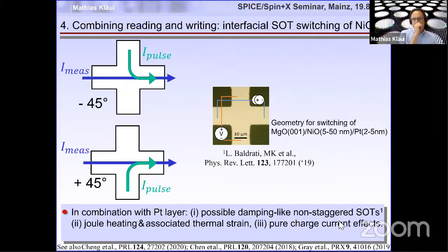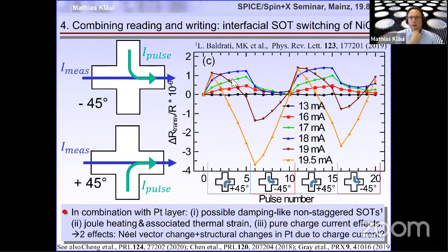And so this is what it looks like. It looks very messy. You have a lot of effects. For small current densities, as shown here, it's more or less flat. There is no effect. Then as we increase the current density, we get this switching which goes up and down, which is like a step-like switching. And then if you increase the current density even further, suddenly the switching of the electrical signal reverses its polarity. And that's really weird, because that means somehow the current density changes the direction of the switching. Is that realistic? We were not the only ones to see that.